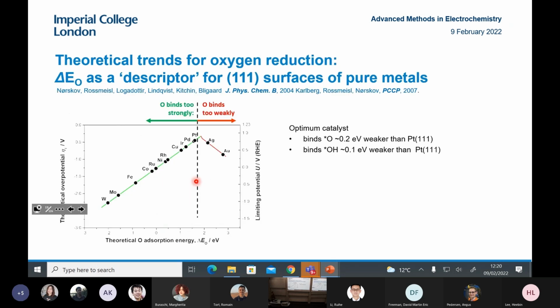However, the good thing about this is it actually simplifies our analysis of the reaction. So this is the theoretical overpotential activity as a function of the binding energy of one of the intermediates, that's oxygen adsorption. You could equally plot it as a function of OH adsorption as well. And what you actually see is that even though it's a complex reaction, you can describe the overall trends simply as a function of this binding energy.